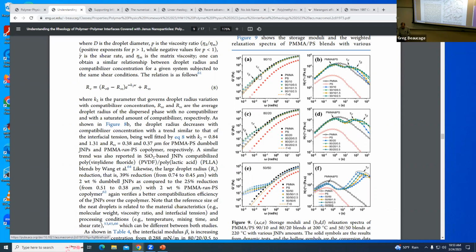And then at that point, you go to this Winter network thing, which says that the storage modulus should be a power law in frequency. And the storage and loss moduli should have the same power law if it's a network. That's Henning Winter, the UMass guy, right? So the guy that Ben Yevitt worked for. Right, so here's that power law showing up when he gets to a co-continuous structure.